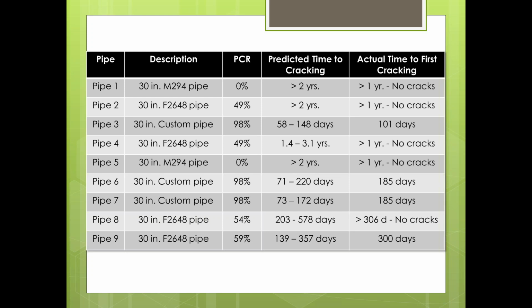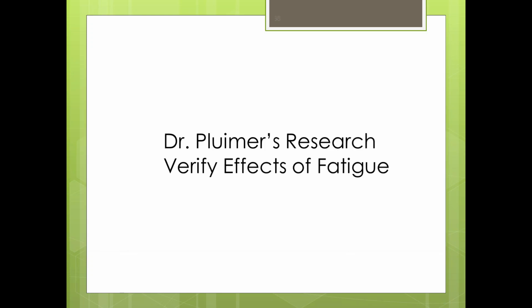There were some that were predicted to see cracking well above and beyond the 2-year time frame, and really no cracking has been seen or witnessed up to that 2-year mark, and they stopped doing the testing at that point because it basically validated the model. So in essence, they really were excited about the fact that the lab testing that was done did a very excellent job at identifying contamination, and that it is very translatable from a predictive service life standpoint to actual field results and when we see cracking in a fully manufactured pipe.